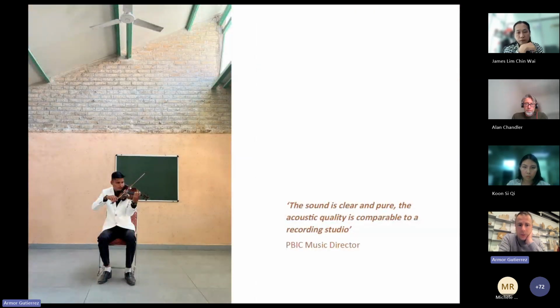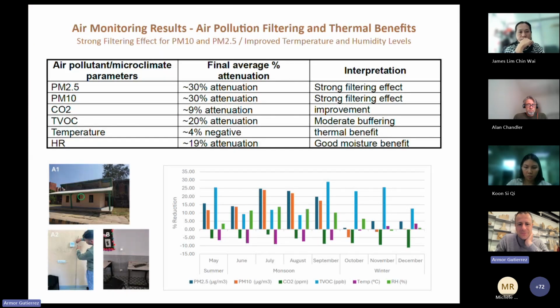Last time we went there, when we officially opened the building, there was a music performance by the music director of the college, and he was really impressed by the quality of the sound. They are used to rooms with no acoustic consideration, where concrete blocks and bricks have been used for the walls, and ceilings are either using plasterboard or directly reinforced concrete, which have very high reverberation times, between 3 and 4 seconds. In Sugarcrete we have around 0.4 to 0.6 reverberation time, which is almost acoustic studio quality, and he was really impressed by the acoustic performance that we were achieving.